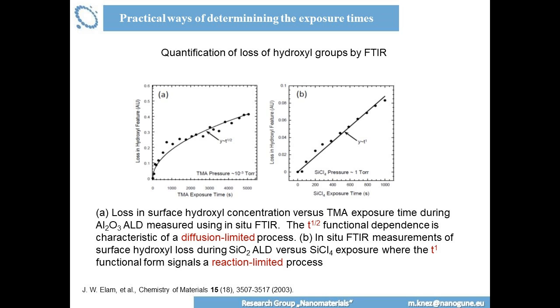The third one is the quantification of the loss of hydroxyl groups. That means you use spectroscopy, you don't use microscopy here. You look into OH functionalities by infrared spectroscopy, for example, and you quantify this just by looking into the peak of OH and how it loses intensity over time. And the loss over time is basically a consumption with the precursors. So in this case, there's a comparison of TMA exposure here, so consumption with trimethyl aluminum, and this is a consumption of OH groups with silicon tetrachloride. And you see that there is a big difference here.